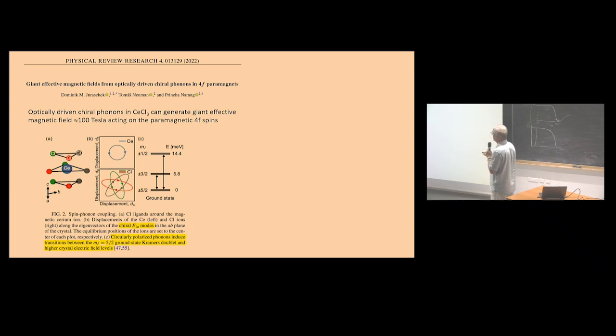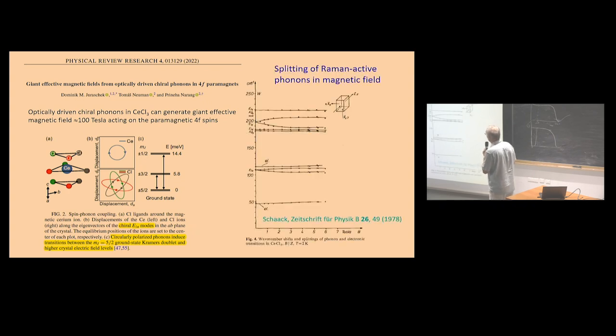Okay, 100 Tesla I don't trust, because they assume, I don't know, 10 megavolts per centimeter amplitude of electric field in terahertz. But it can. There is another paper studying cerium trichloride, and they observed a magnetic field of 3 Tesla. So it is also a strong effect. This prediction that it can be valid is also supported by observation of splitting of Raman active phonons in magnetic field. Classically, if you have a system, magnetic or ferroelectric, does not matter, the splitting of phonons does not appear in magnetic field. You can maybe shift it.